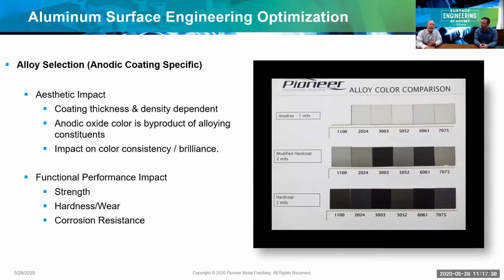You know, and that aesthetic impact can also be seen when you do an overdye. So if you look at the chart at 1 mil thickness of anodizing, you get different hues. And if you use these different alloys together and try to make all the parts blue, for example, you get a little bit different shade or a little bit different hue of blue based on the alloy. Same can be said, and we touched on the 2000 series alloy and its limitations as well as cast, but 2000 series with copper not being able to produce a real thick, say, 2 mil, MIL-8625 requirement type hard coat, and therefore your wear resistance, your corrosion resistance potential is limited. So something to consider as you go about selecting alloys and considering the cost impact, the machinability, and everything that aligns vertically with the desired outcome of the part.